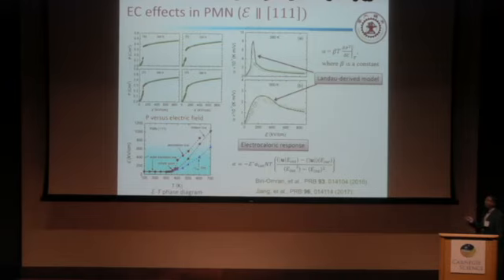Then we also use the Landau-derived model to fit our EC coefficient as a function of electric field. We can see that this model gets a very good fit to our data. Next, we calculate the alpha max as a function of temperature. We find near the critical point a giant electrocaloric coefficient. This agrees well with what the experiment found.